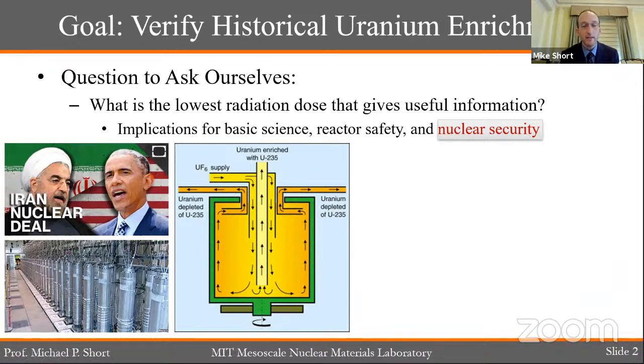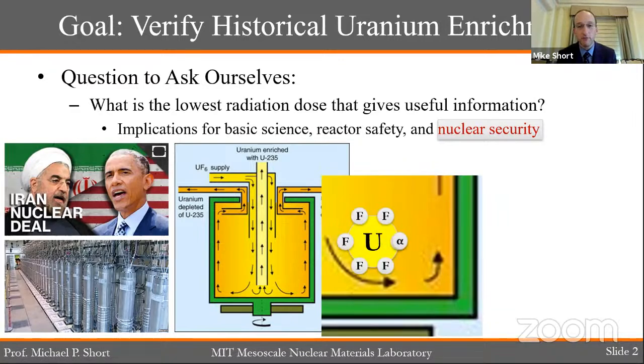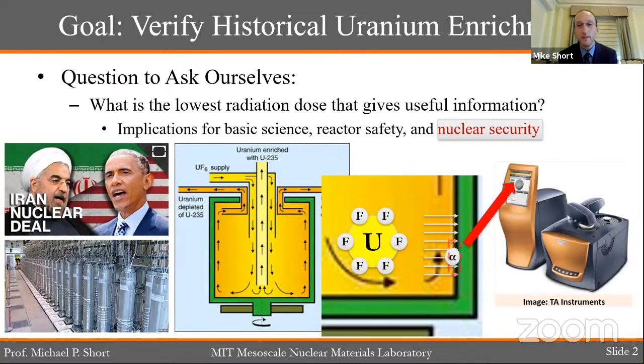And our technique lies in the fact that at the walls of these centrifuges, alpha particles or little bits of radiation are being given off by the uranium all the time, imparting damage to the inner walls of these materials. And if we can then scrape off those inner walls and put them in some instrument and measure how much damage was done, we can reconstruct how much irradiation they incurred, how much UF6 flowed through, and therefore how many weapons a nation or state may or may not have made.